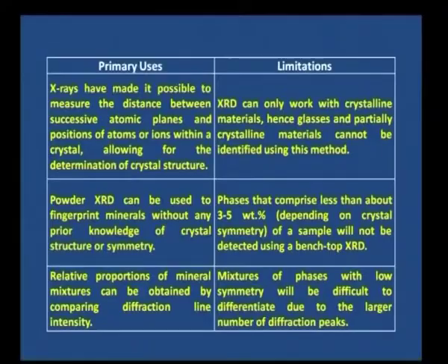Powder X-ray diffraction can be used to fingerprint minerals without any prior knowledge of crystal structure or symmetry. The minerals contained in a material sample can be known using powder XRD. Okay. Then the phases that comprise less than about 3 to 5% weight percentage of a sample will not be detected using bench top XRD. There are some limitations. Relative proportions of mineral mixtures can be obtained by comparing diffraction line intensity.